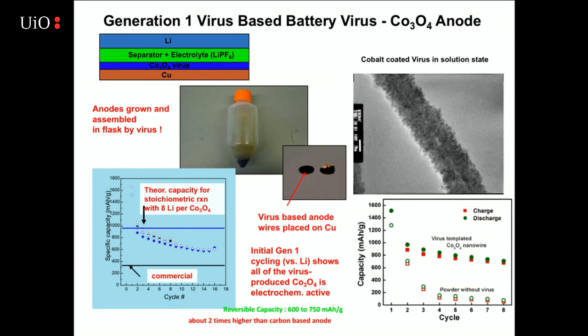And this is a commercially available nanomaterial. This is a theoretical capacity for 8 lithiums per cobalt oxide. And you can see that we hit theoretical capacity, but as we started to cycle, it started to fade.